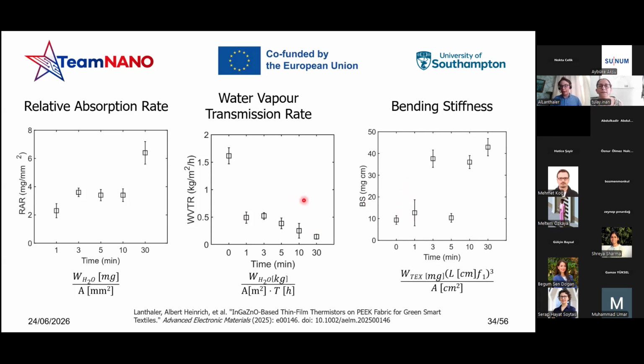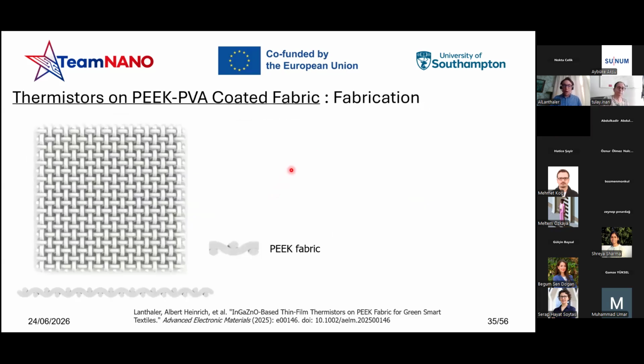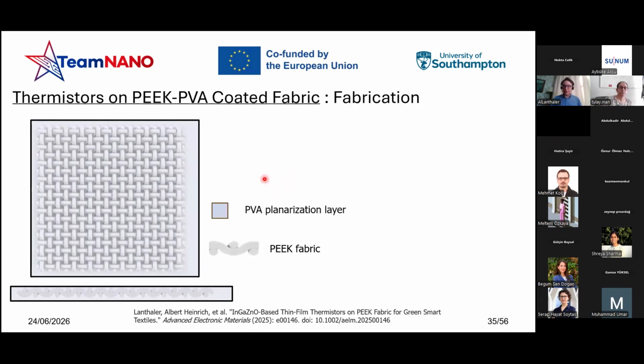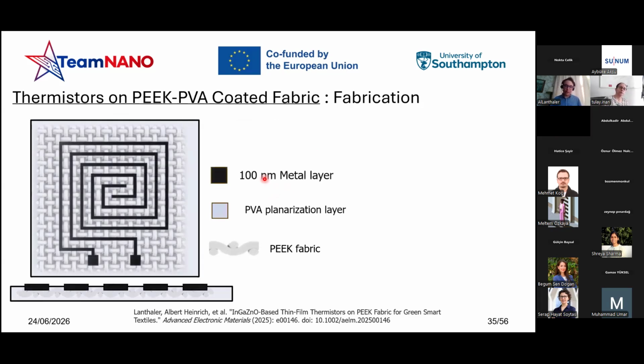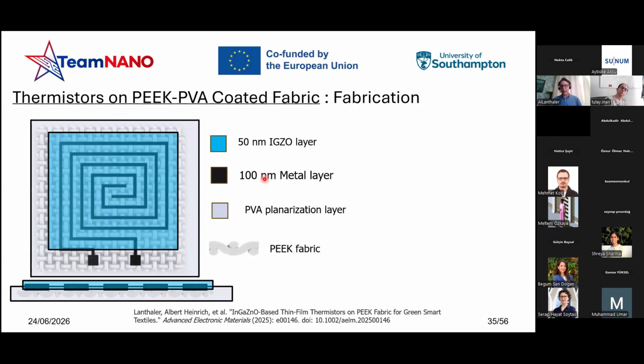As you can see, there's a pretty clear trend. The longer we dip the PEEK fabric into the PVA solution, the higher the material absorbed, but of course the breathability decreases as well, and the bending stiffness becomes greater. So what we have decided is to, for the moment, keep it simple and stick to the thinnest layer possible. After that, after the PVA planarization layer, again, we place it into the sputtering machine and we deposited a 100 nanometer thick layer of metal. And after that, again, a 50 nanometer IGZO layer on top of it.